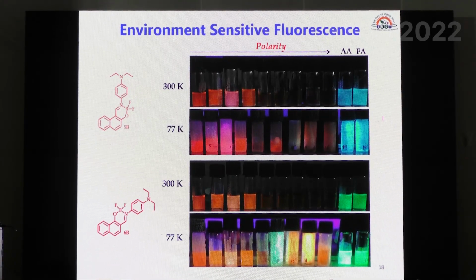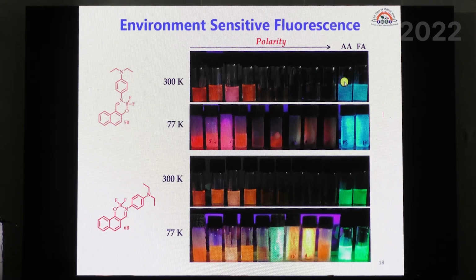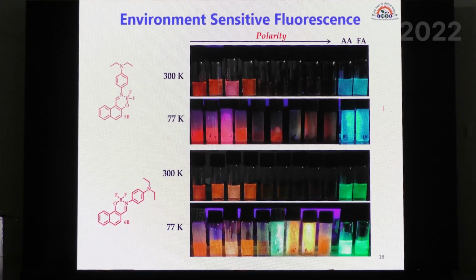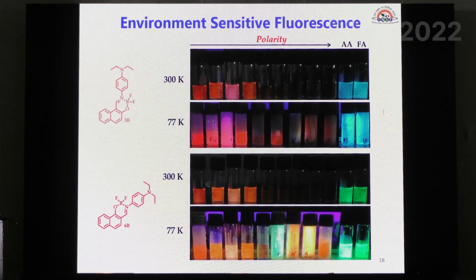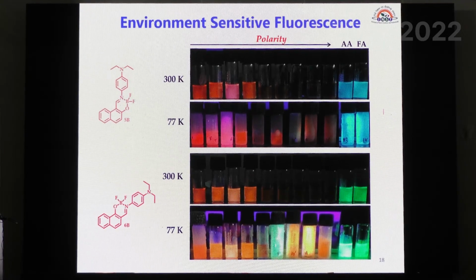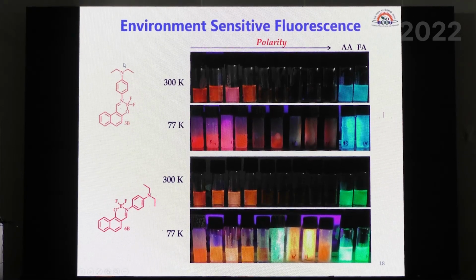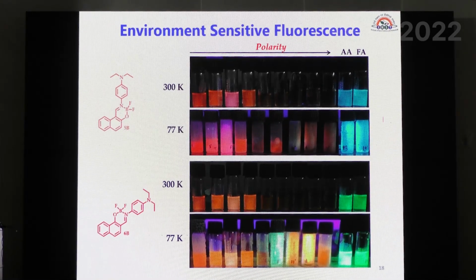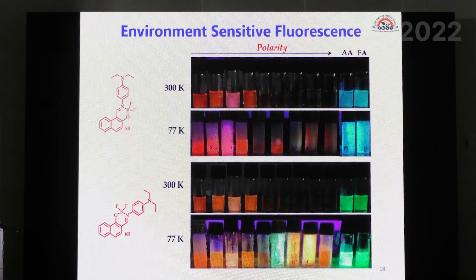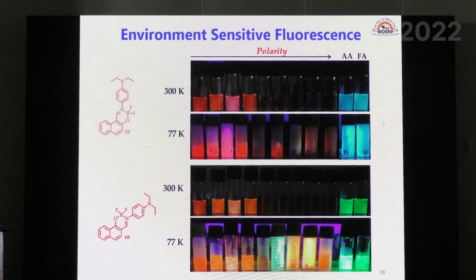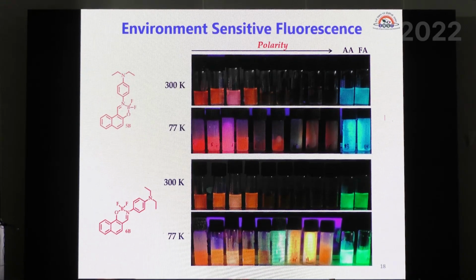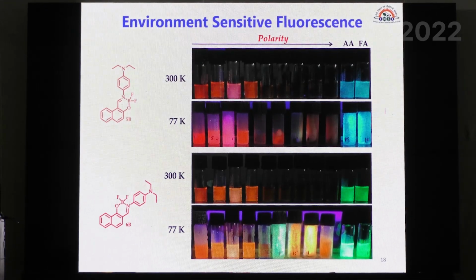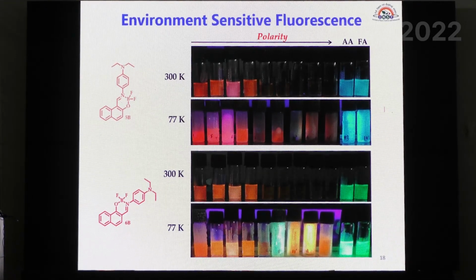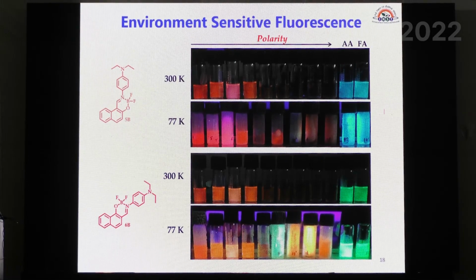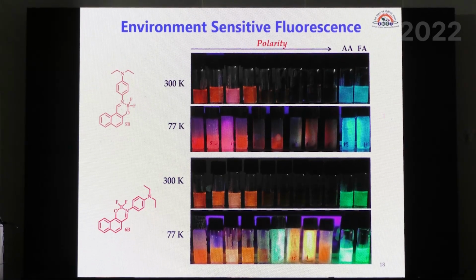Basically this is a fluorescence color. And in acids, these are acetic acid and formic acid, they give a completely different color. The reason is that when you have acid, this amino group gets protonated, and that prevents the charge transfer property. As a result, you get an emission from the monomeric form or the singlet locally excited state. Because of that, we see a drastic color change from, say, orange or reddish color to either bluish or greenish in nature.